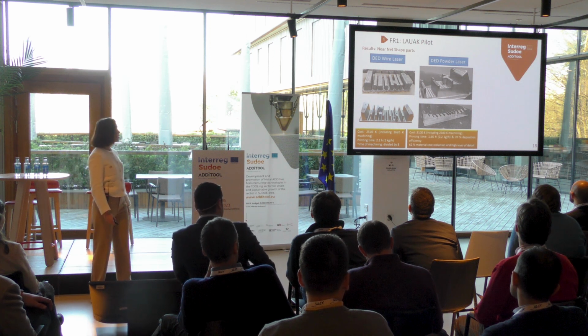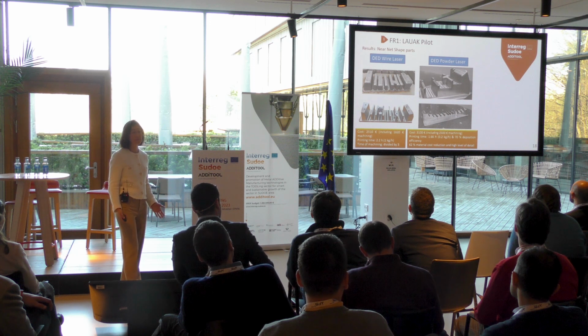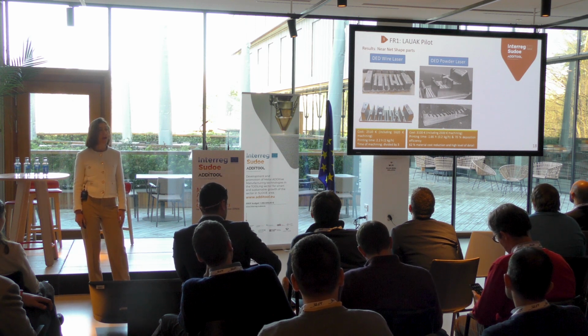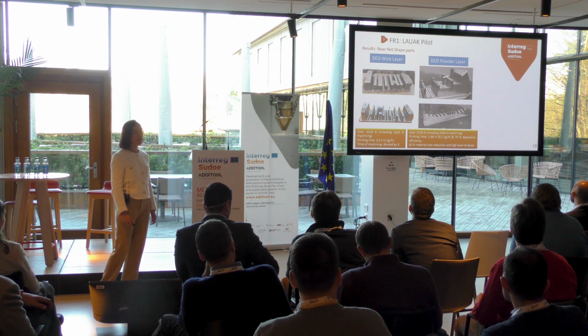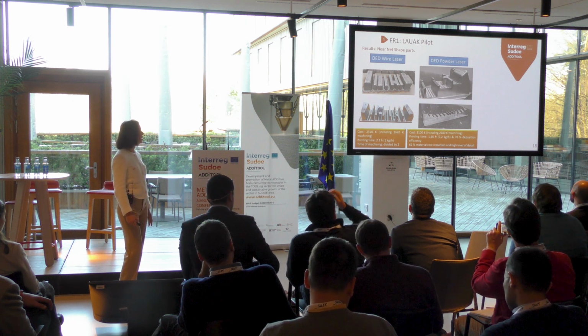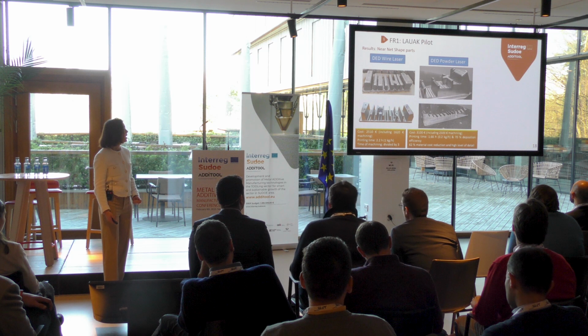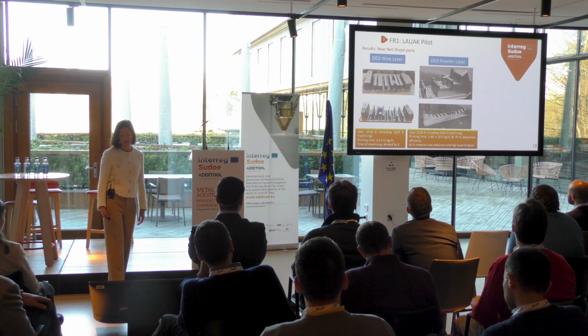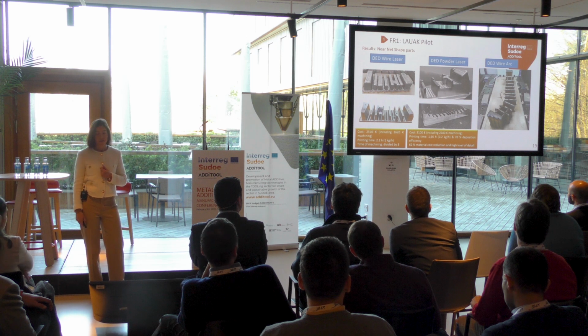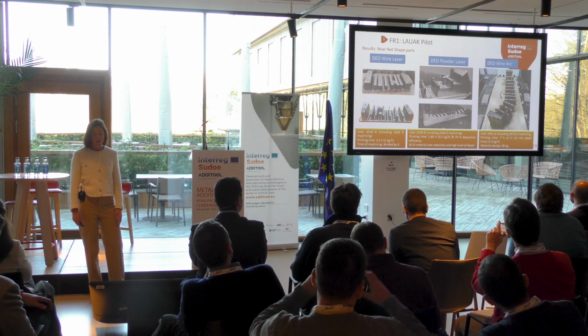In the case of the powder laser, you can see the cost, again being mainly due to the machining step. The printing time was less than 2 hours, with a deposition efficiency of the powder of 70%. The most highlighting point here is that we could use a lower cost base material, 62% less in price, and we could obtain a high level of detail. Finally, with the DED wire arc, the cost is the highest for the bigger part.